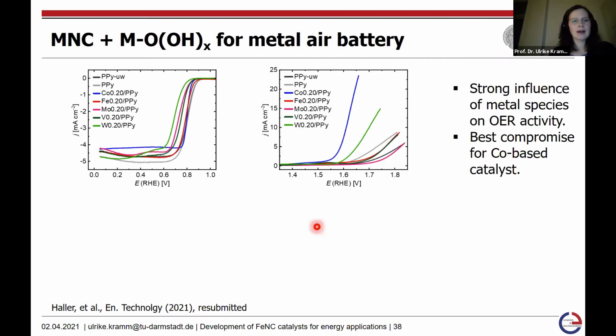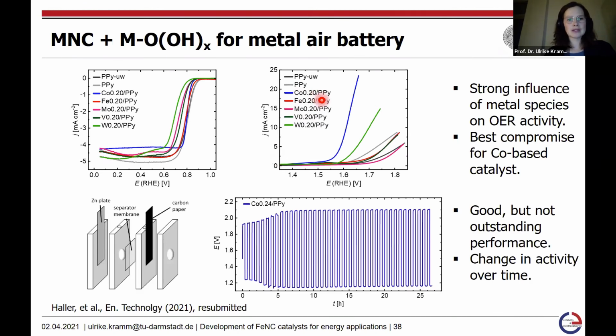So Steffen then varied the different metal centers for this type of catalyst material. Here is the oxygen reduction reaction activity, and here is the activity for the oxygen evolution reaction. And there we can see that the effect of the metal center on the performance is much more pronounced for the oxygen evolution reaction, where the cobalt case worked out best. And that was also why he selected the cobalt-based catalyst material for further optimization, and then also applied this in a metal air battery, so in a zinc air battery.